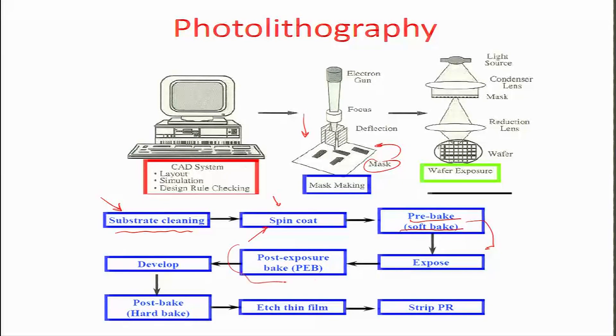After exposure, you heat-catalyze the bonding mechanism — for negative tone resist, there is cross-bonding, which gets further affirmed by post-exposure bake. Then you develop the film surface. For a negative tone resist, the areas exposed remain while the rest are etched off during development. After development, you post-develop bake to get rid of all liquid — particularly the developer solution — from the surface. Isopropanol is typically used to check if residual unexposed resist remains; if it turns whitish or cloudy, resist is still present.